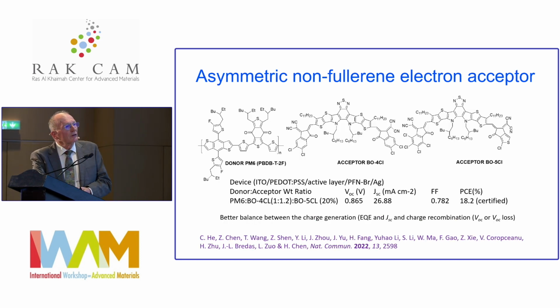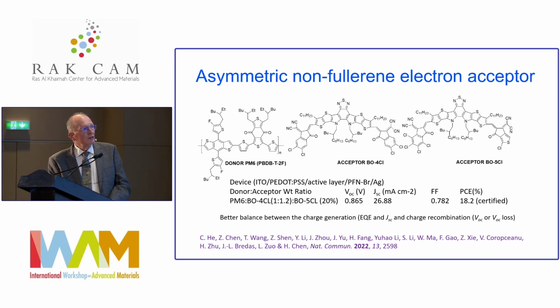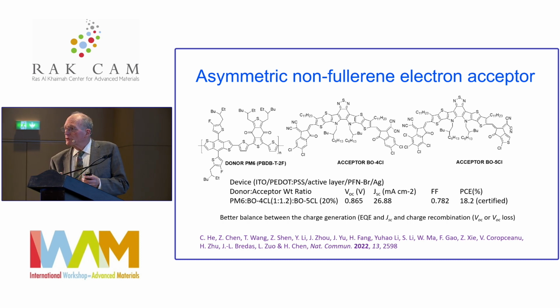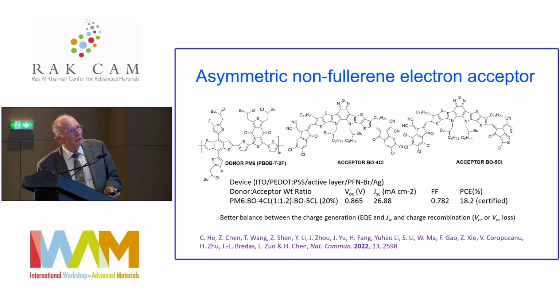Now, what about this non-fullerene acceptor? What else has been done here? Well, one of the other tricks is to make the acceptor influenced by a third component in which symmetry is broken. If you look carefully at this, the donor is pretty similar to the structure I showed you already on the previous slide, but the acceptor consists of a blended mixture of, that's pretty much the Y6 molecule, except with a number of chlorines on these rings, and an acceptor where this ring here is changed from the benzene ring to a heterocycle, and that's blended in a fraction of 20% of the mixture. So it's a one-to-one combination of these two components, donor acceptor, plus a 20% weight contribution here, and 18.2% was the result.